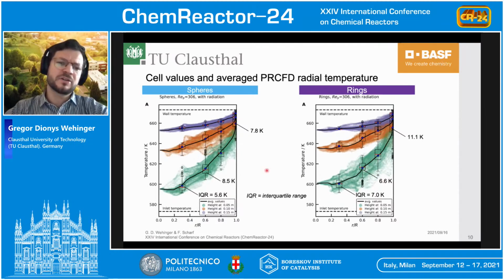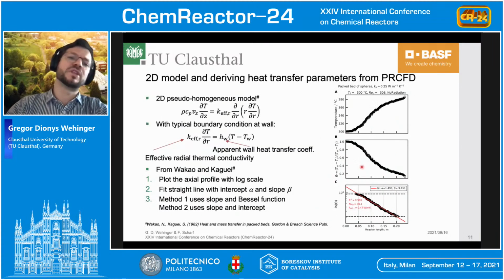Then I want to give you an idea about how the azimuthal distribution looks like. So that means on 3 different levels inside the bed, I draw you in black the average velocity, the average temperature, as well as all of the temperatures on this cross section. And as you might see, we have pretty large interquartile ranges, ranging from 5 to even 11, very close to the wall. So in other words, although we see here this average value, we still have a large distribution at a certain point due to the azimuthal differences.